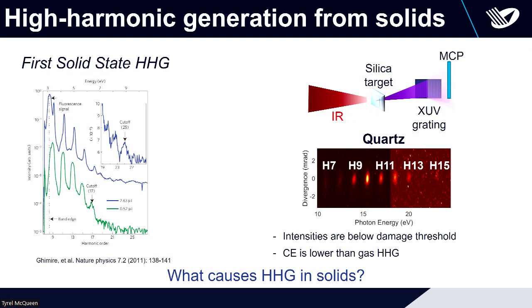This is one example from our lab where we go to about 30 electron volts, 25, that's 50 to 40 nanometer. So it's still pretty high energies, but not nearly as high as we can go with gas harmonics. Still done at intensities that are below the damage threshold, but at conversion efficiencies that are much lower than in gas HHG. The pictures how that works are relatively similar. You can also say you create an electron in a hole, which you now accelerate in the bands and recombine.